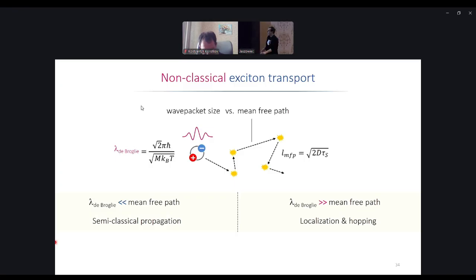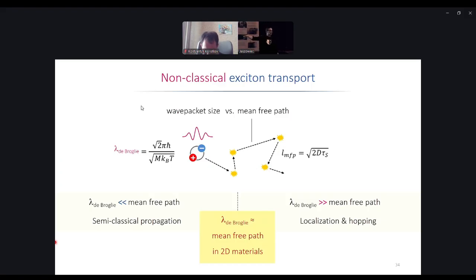And quite interestingly, a lot of semiconductors that people are studying these days, especially the fundamental materials, the transition metal dichalcogenides and the perovskites, have de Broglie wavelengths roughly in the range of the mean free path. So it becomes even questionable whether this drift diffusion approach is even applicable. Which means that certain transport phenomena need to be calculated more accurately and not using these simplified semi-classical models. And hopping, of course, also doesn't help us because we are in this intermediate range.